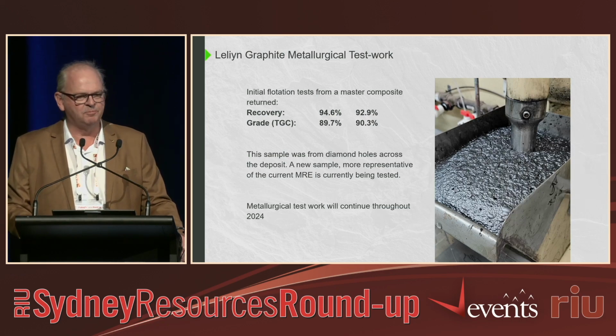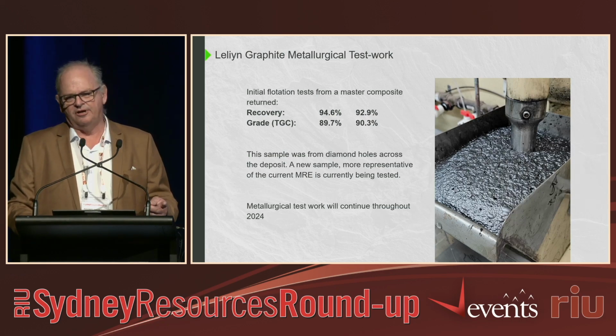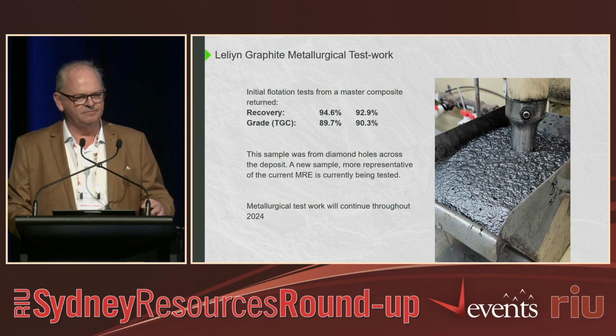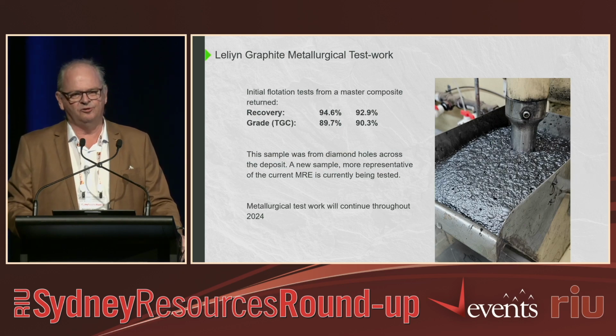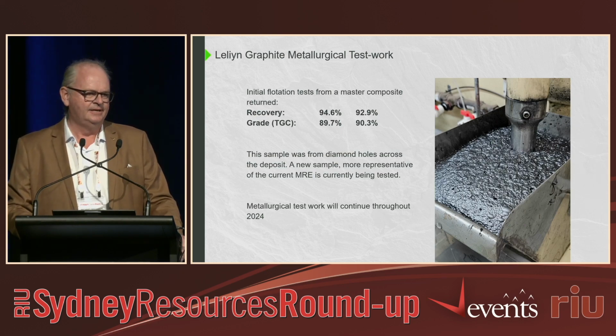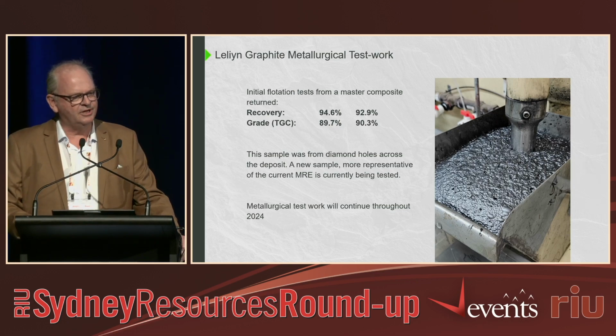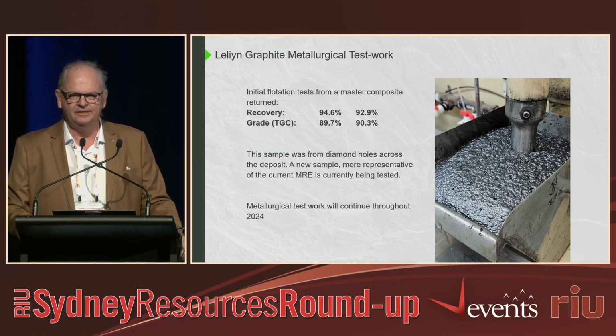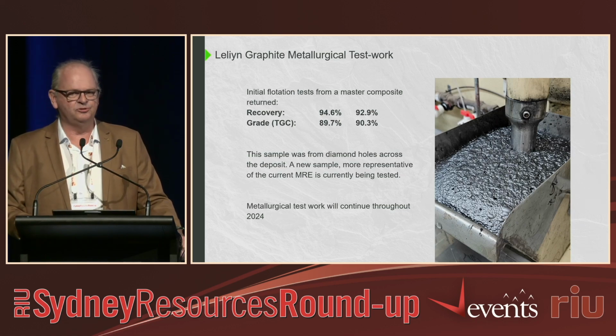We're close to optimising grind size, grind time, reagent dosages and viscosities and things like that in the flotation to maximise that, or to optimise it. So we're very confident we'll get a concentrate grade of around that 95% mark, and once we achieve that, we'll produce a batch of concentrate, maybe 15 to 20 kilograms, and we'll get that sent off to a lab, maybe in Europe at this stage, to get some further testing done to assess the viability to produce a battery anode material.